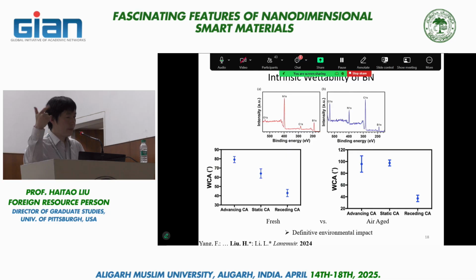The initial contact angle is around 60 degrees, but after several hours of air exposure, we started to see a contact angle around 100 degrees. So the same kind of effect we saw in previous studies on other 2D materials, we again saw for boron nitride. I also want to mention that after our work, many other research groups have reproduced our measurement on graphite and graphene, and also extended the study to a wide variety of 2D materials, TMDs in particular. So I want to wrap up.